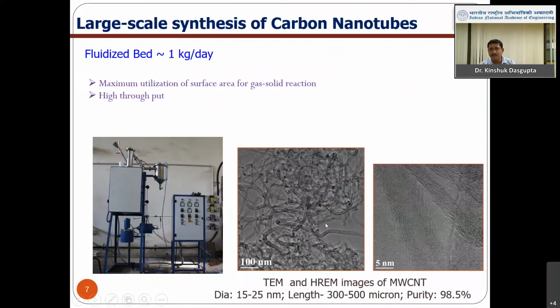And how carbon nanotubes look, means it is nano. That means the diameter is in the nano dimension, but the length can be in the micron or in the millimeter. So if we see under electron microscope, this second image is the electron microscopic image, TEM, transmission electron microscope, where you can see a tubular kind of structure where the core is hollow. And if we go for further high resolution, that is high resolution electron microscopy, you can see the number of walls of carbon nanotube. And by this method, we are able to produce almost 98.5% pure carbon nanotubes.